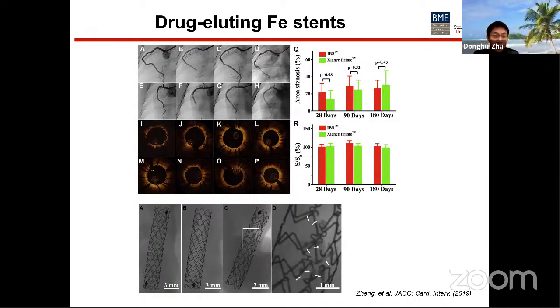From the QCA, the quantitative coronary angiographic imaging on top, the middle is OCT imaging, and the bottom is micro CT imaging. These data show that the drug-eluting iron stent so far is very good, comparable to the benchmark control. On the right side is the percentage area of stenosis, the ratio of scaffold area at follow-up compared to the initial post-implantation value, also comparable between these two stents. So far, the performance of the drug-eluting iron stent is, if not better, very close to the benchmark control. This is a good sign.